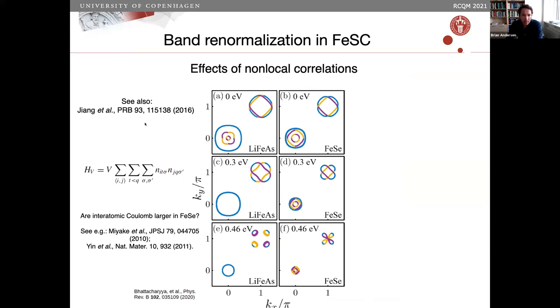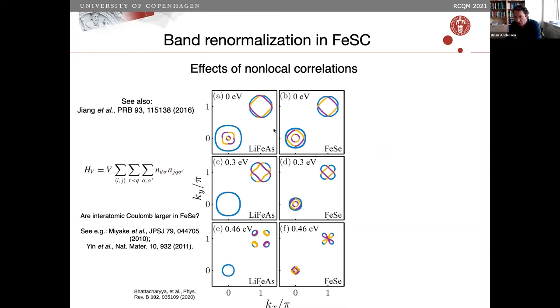What has been known for a while — starting as far as I know from this paper — is that non-local correlations do this quite naturally. For example, if you just include nearest-neighbor Coulomb repulsion and apply a mean-field decoupling, you immediately get pocket shrinking. I'll go through this in quite detail in a few slides. Straightforwardly, you get very small pockets and these propeller shapes for iron selenide. Doing the same thing for LiFeAs doesn't generate the same result — it depends very much on the starting band structure. Of course we enter the discussion of whether longer-range Coulomb is really larger in iron selenide than in other materials — perhaps due to the missing spacing layers and less screening — this is unknown, but there are some calculations pointing to that effect.